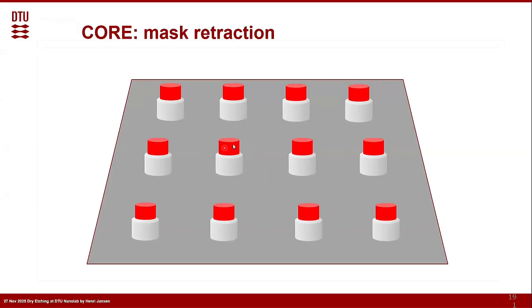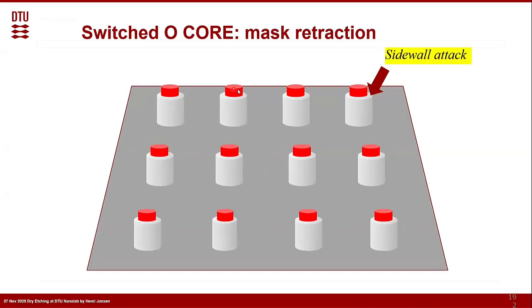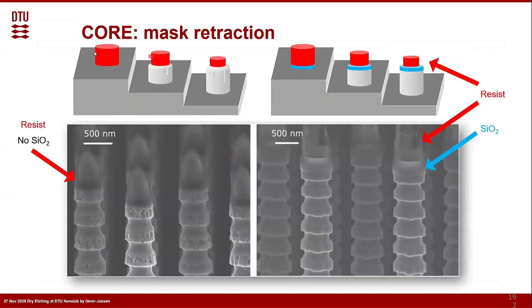In the beginning, we will go maybe nicely down, but because of the oxygen in our silicon etch process in the core, the resist will also what we call retract. It's not only etching from the top side, but also sideways, because the radicals are etching it away from all directions. It's isotropic. But that means that after a while, the retraction is so much that the top side, which was originally there, is also going to be under attack. So after sufficient etching, deeper and deeper, the sidewalls are going to be under attack, where the resist is slowly retracting. You can prevent that by, for instance, putting a silicon oxide on top, which protects the top side, and then it will stay nicely clean.